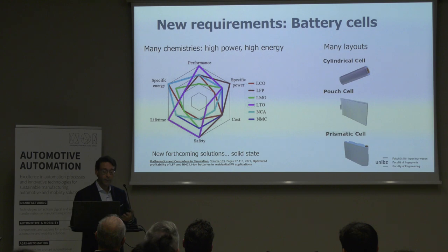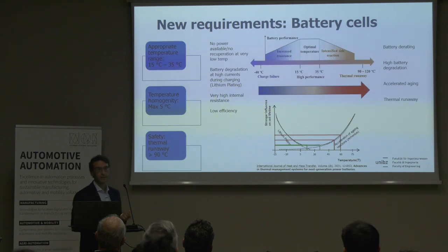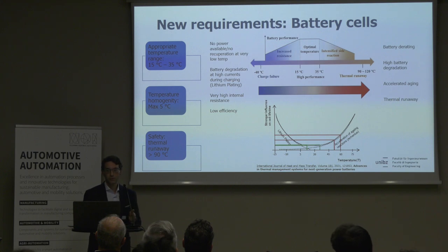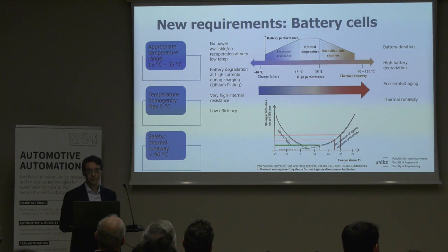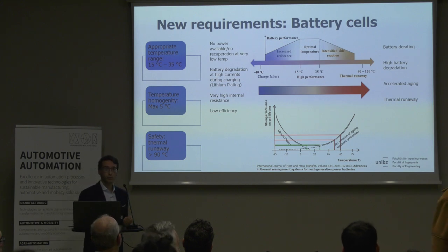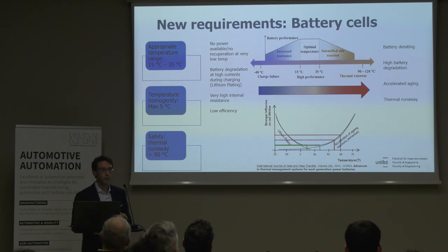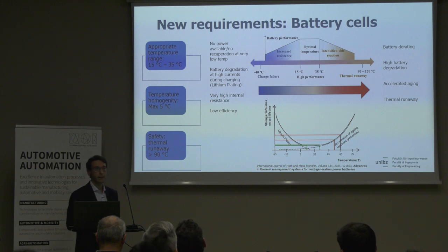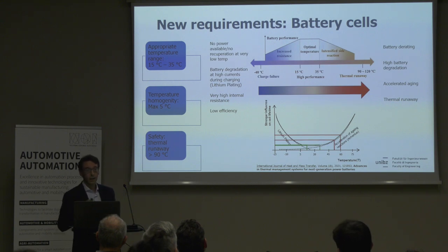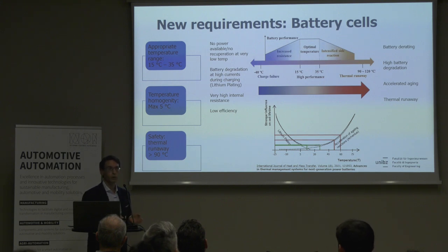Of course, every choice influences the thermal management system a little bit, but besides this, in general, all batteries like to work in a very narrow range of operating temperature, typically between 15 and 35 degrees Celsius. If we go below, the problem is the higher internal resistance, so lower efficiency. Moreover, batteries don't like high currents at low temperature, so fast charge is not nice, and energy recovery too. And if we go really below a certain level, we also have the risk of reduced capacity or even the impossibility to use the battery. If we go up with the temperature instead, the problem is mainly degradation and very quick aging of the cell, so it will shorten its lifetime. If we go above 90 to 100 degrees Celsius, then we also have safety issues.